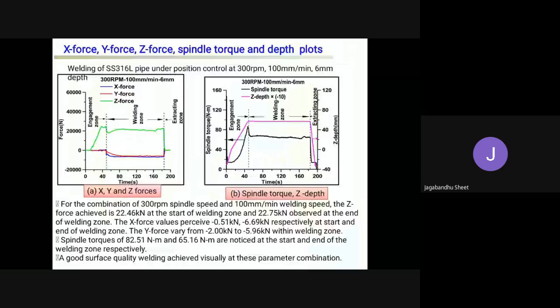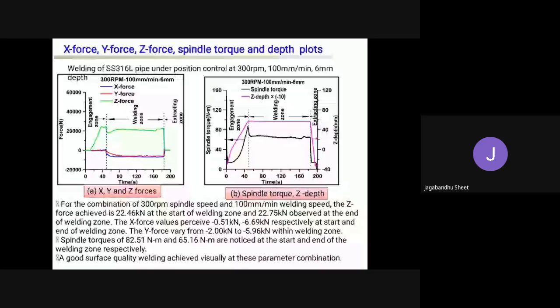The first set of process parameters. Here you can see the three different zones: engagement zone, welding zone, and the extracting zone. For the combination of 300 rpm spindle speed and 100 millimeter per minute welding speed, the Z force has been achieved 22.46 kilonewton at the start of the welding zone and 22.75 kilonewton at the end of the welding zone.